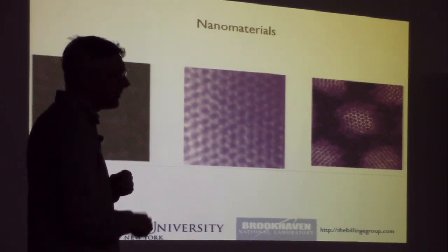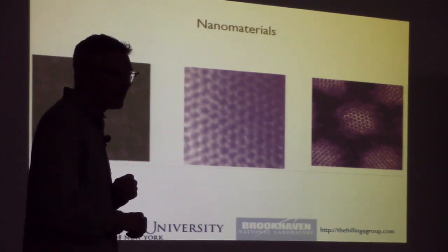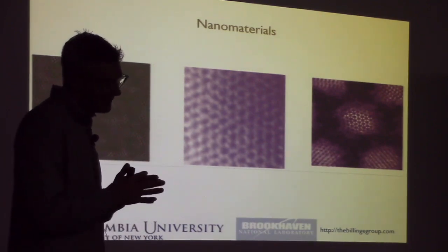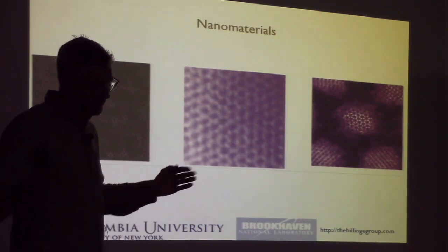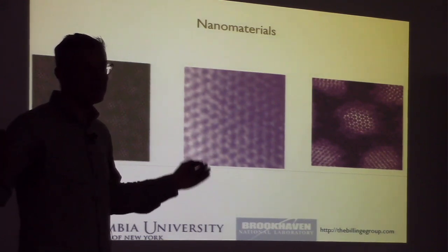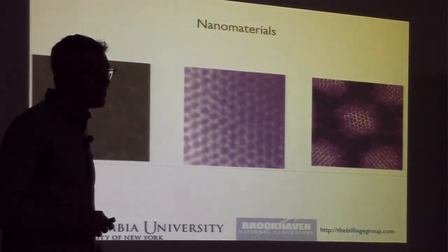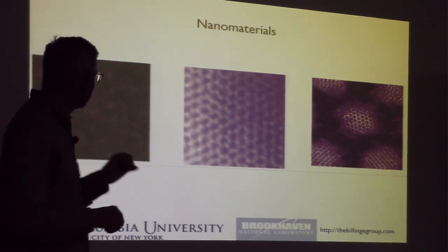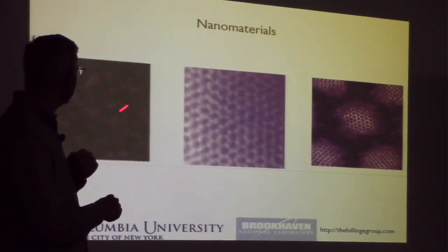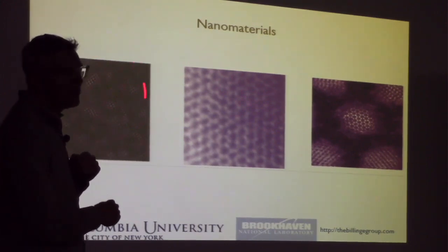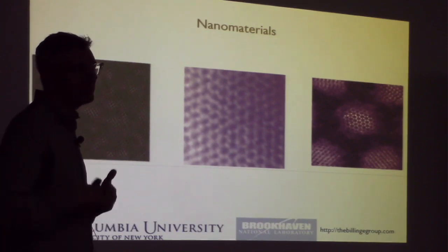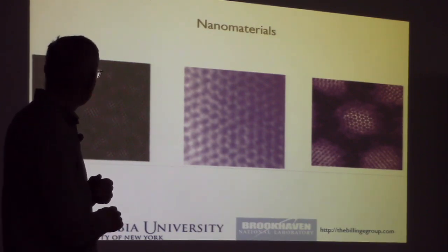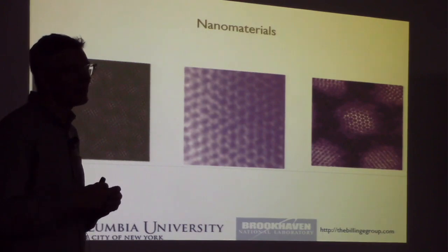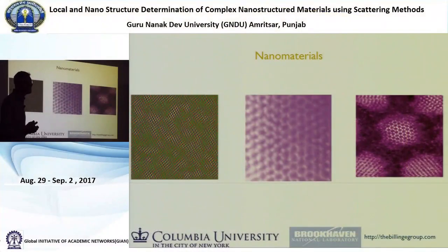This is a nanostructured crystal. So this is a material which has crystallographic long-range order. It's actually a beautiful crystal. But when you look at it with PDF, you look down in the local structure, you see this kind of tweed-like structure. And what's happening here is you have these nano-sized domains where the structure is modified from the average structure.